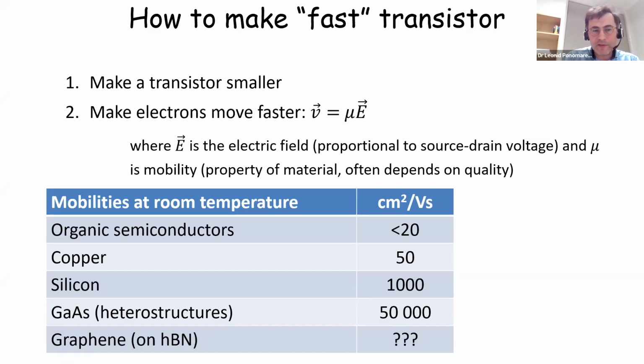Different materials have been used in semiconductors. Organic semiconductors are quite popular, but they usually have very low mobility, so there is no way of making very fast devices using organic semiconductors. Popular metals such as copper or gold cannot be used in field effect devices, but the mobility in these materials is of the order of 50. In silicon, the very popular material of choice at the moment in the semiconductor industry, it is about 1,000 centimeters squared per volt per second. So there are materials which are much faster than silicon.